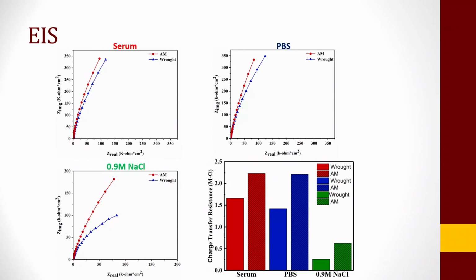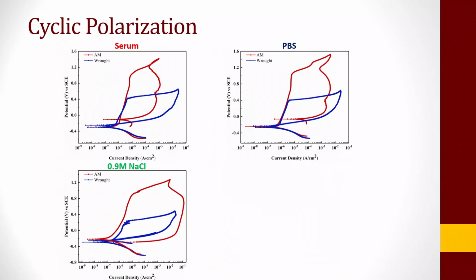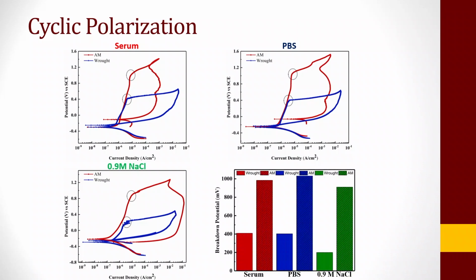So similarly, when you look at the charge transfer resistance obtained from these graphs, you could see that the charge transfer resistance in serum, in PBS, and also in 0.9 molar NaCl is higher for additively manufactured as compared to wrought counterparts. Similarly, when we look at the cyclic polarization curves, that clearly depicts, if you look at the breakdown potentials, by the way, all the 3 blue curves are for wrought and all the 3 red curves are for additively manufactured samples.